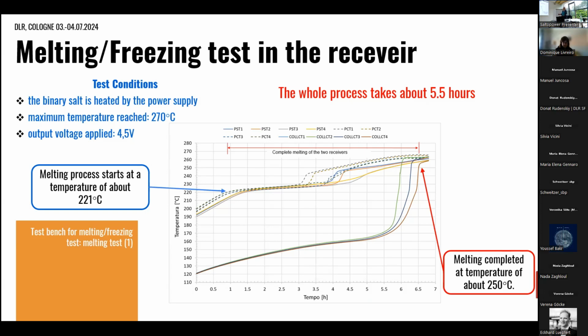Inside, in the middle section of the two receivers, and in the collector welded between the two receivers. The whole process takes about 5.5 hours. We can see that the process starts at a temperature equal to 221 degrees and finishes more or less here, at a temperature of about 250 degrees.